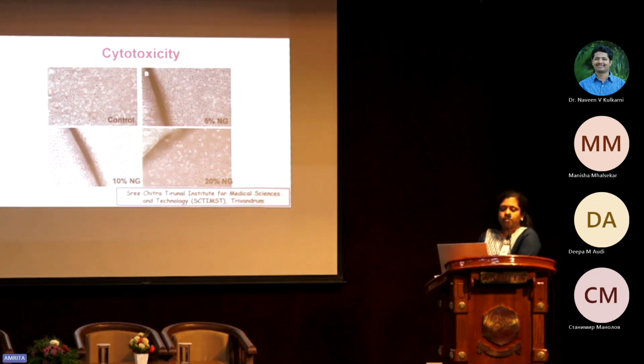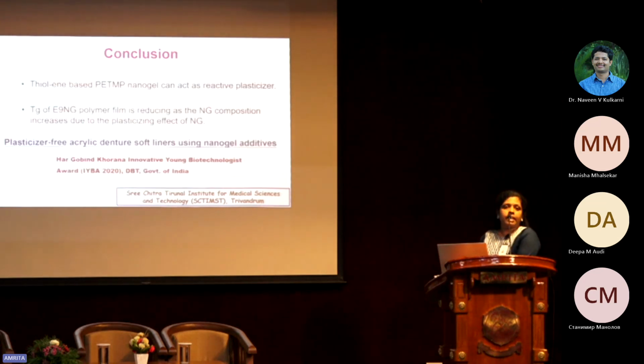We just published this paper. And in conclusion, the thiol-ene based PETMP nanogel can act as a reactive plasticizer, and the TG of this system film is reducing as the nanogel composition increases due to the plasticizing effect of this particular nanogel. So different aspects of this particular study are going on. For example, how we can use it in constructing the blood bag, or how we can mitigate the plasticizer migration in blood bags.